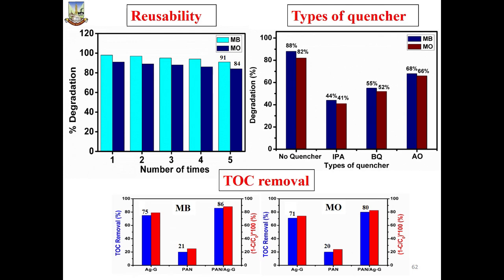For reusability, we have used different quenchers, and we have done a cyclic study. Methylene blue shows 91% degradation, while methyl orange shows 84% degradation. A very marginal decrease in the degradation rate is observed, and even after the fifth cycle the material does not lose its catalytic activity. It is very highly porous.